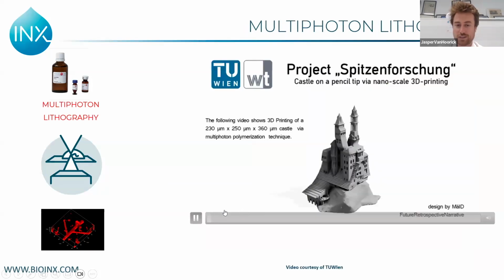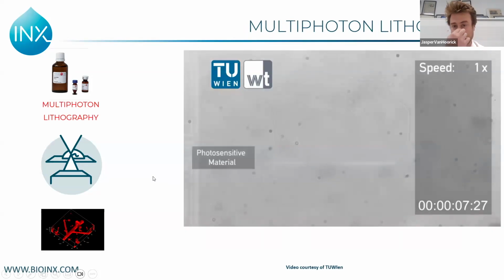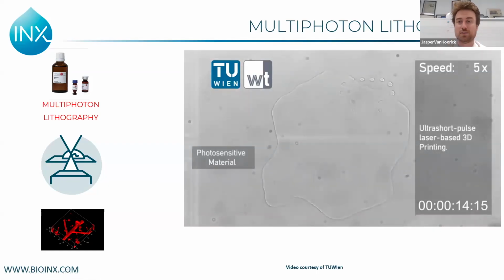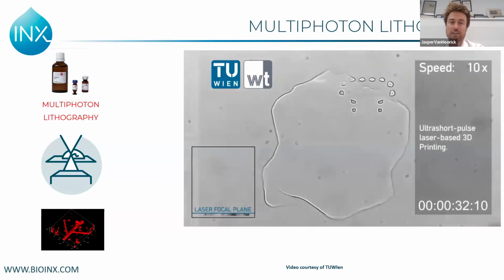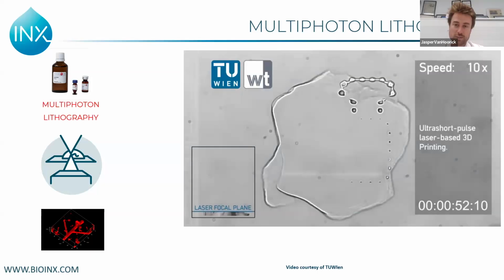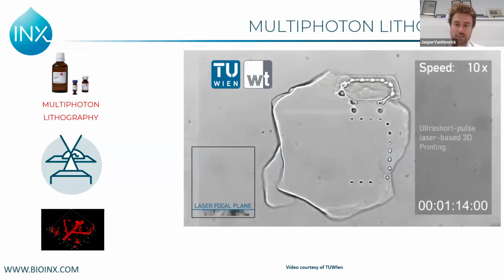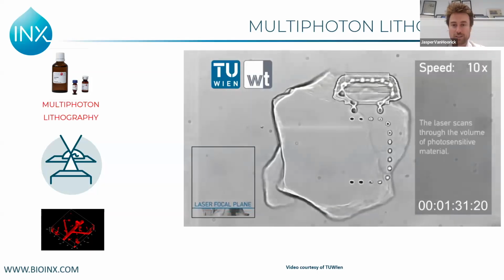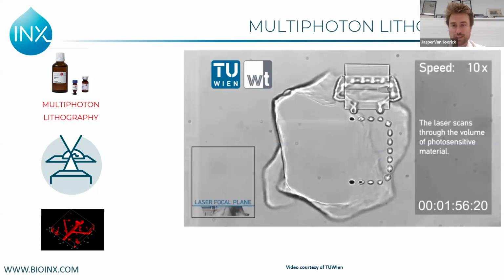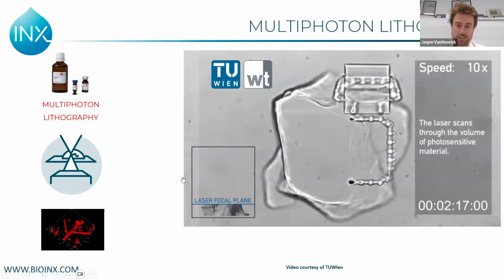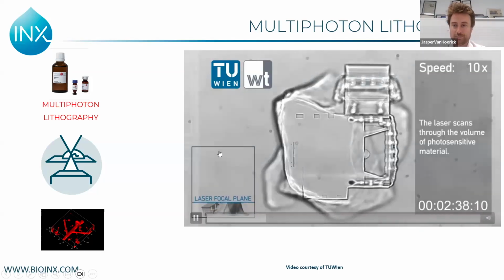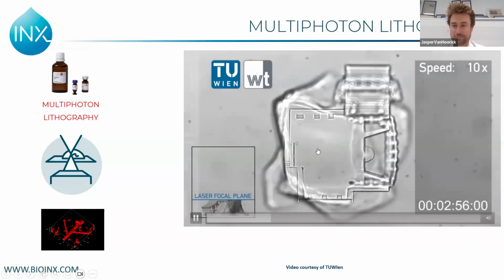So that's the theory, but if you see it in practice, you can see how impressive this is. This is a movie which was recorded at TU Wien in Austria in the research group of Alexander Ovsyannikov, where they actually printed, showed the potential of the technology by printing this small castle here. You can see in this case it's